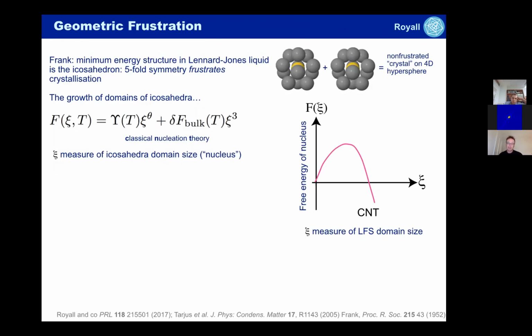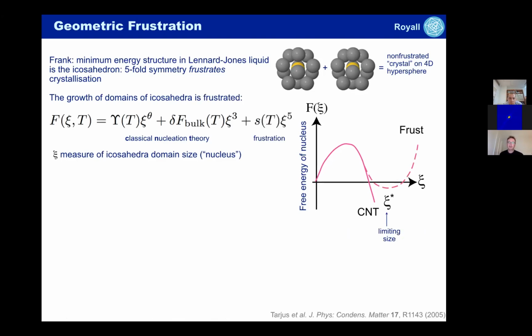The second theory I want to tell you about is geometric frustration. Now, it turns out that in a liquid, when you reduce the temperature, the material often wants to form shapes called icosahedra. Icosahedra are like 3-dimensional pentagons, and they consist of 13 particles organized in an icosahedral form. And what we imagine is, as we drop the temperature, it's a little bit like freezing into a crystal. So the system wants to form icosahedra, it'll want to form domains of icosahedra. But the problem that we have is that as these domains of icosahedra grow, because icosahedra do not tessellate, at least they don't tessellate in Euclidean space, then rather than a crystal nucleus, which would just grow and grow and grow, the icosahedra domains become frustrated as they grow, and they can't grow very much.